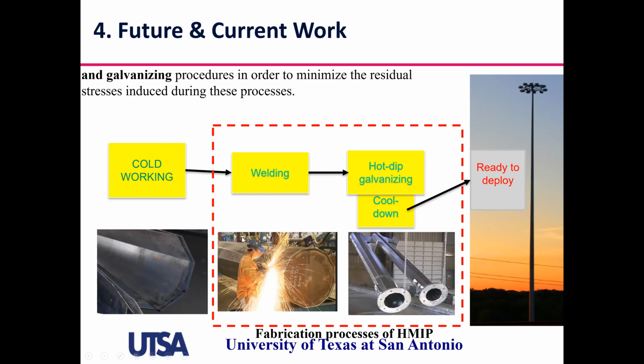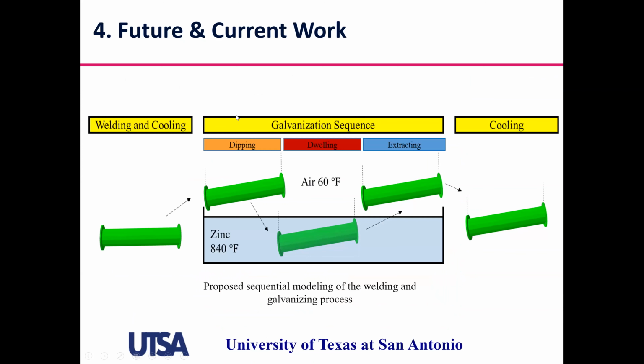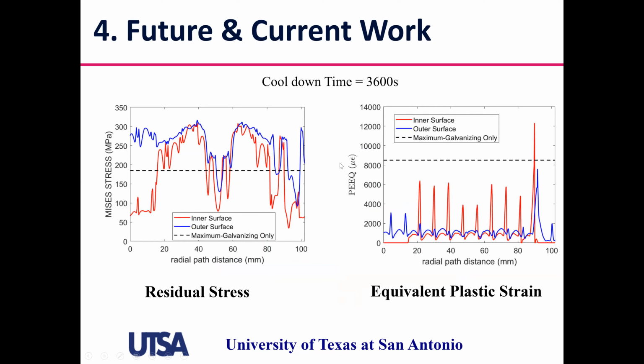So under this new grant, we incorporated the effects of welding. And we had this metal part already simulated, and we added this part to the simulation, both welding and cooling. And here I showed the stresses and the equivalent plastic strains through a path. The horizontal line indicates the maximum stresses and plastic strains that we were obtaining just during galvanizing, and then what would be the resulting stresses and strains once you have welding plus galvanizing. And as you can see, there are some higher values by introducing the welding to the simulation.